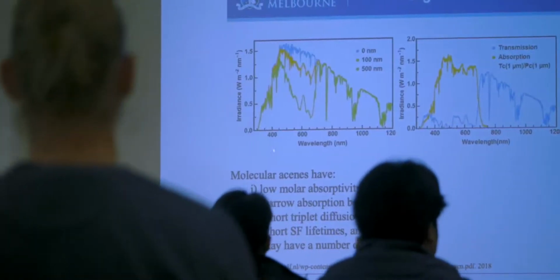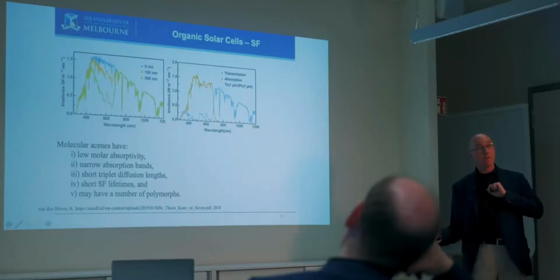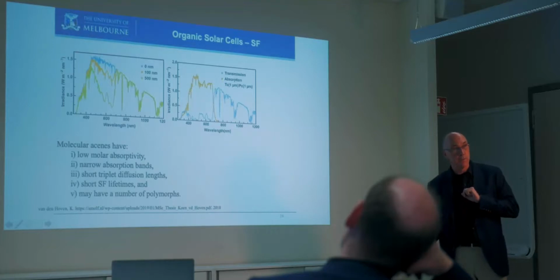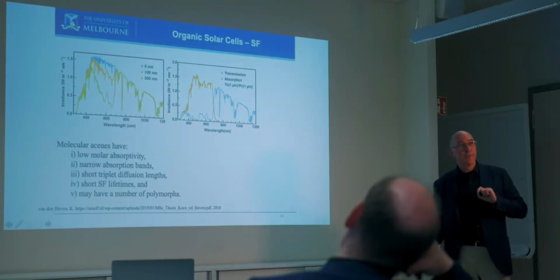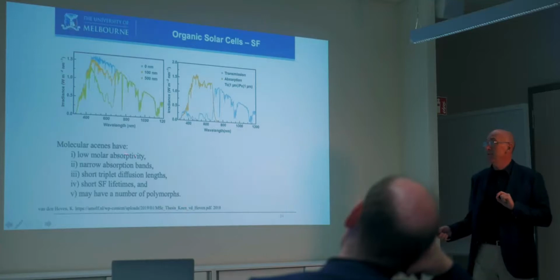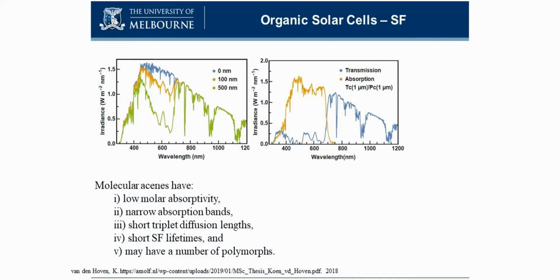500 nanometer, this much light. To absorb all the light that we want to do the singlet fission with, we need a layer which is 1 micron of tetracene and 1 micron of pentacene. But of course, we have issues with that, and this is because we have low molar absorptivity. The triplets have a short diffusion length and a short lifetime. And so if we have a film that thick and we generate a triplet at the top, we'll never be able to collect it at the bottom of the device because it's just too thick.